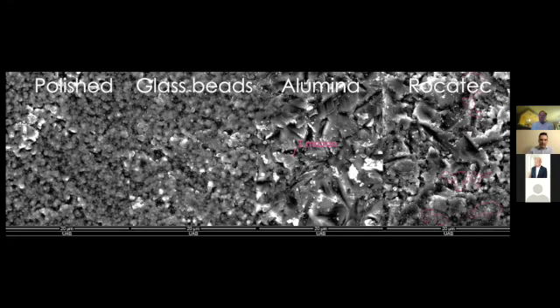Some people think Rocatec is going to be softer than alumina particles. Rocatec, though, is basically just alumina with a light dusting of silica on top of it. What it does is embed silica into the zirconia. Once you've got silica, which is the same thing as glass, you can now use silane to bond to that embedded silica. For me, I feel like it's an unnecessarily complicated way to bond to zirconia. It's easier to just sandblast it and then bond to it with MDP. But a lot of people ask about Rocatec, so I just wanted to show the picture.